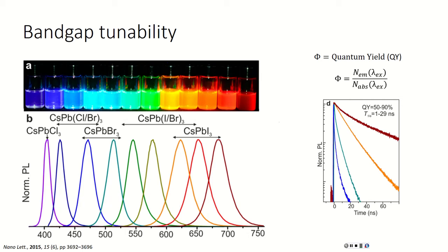Same process, super easy. Organic materials, you have to create different dyes at specific wavelengths. For nanomaterials, if you change the size, you directly change the band gap, which is the big benefit over organic material, which you can't do readily.